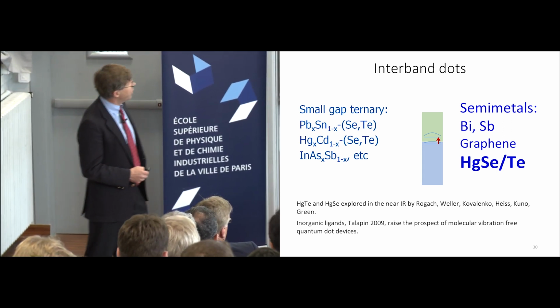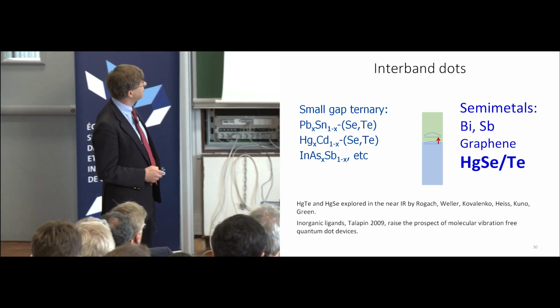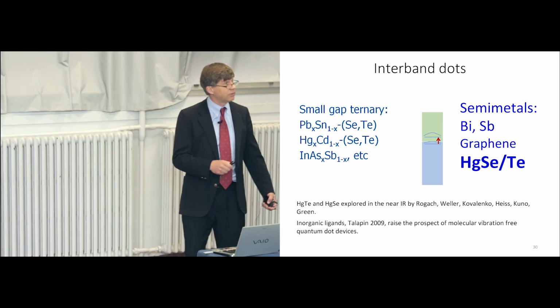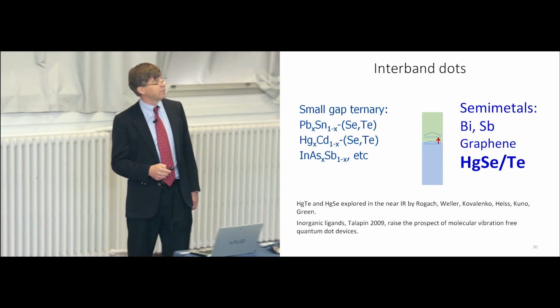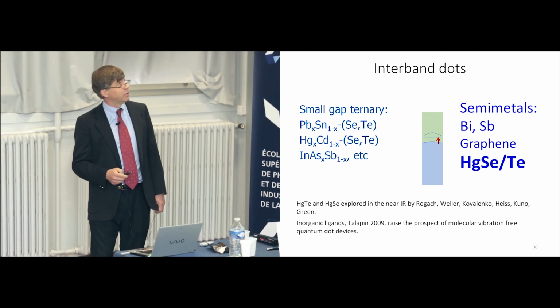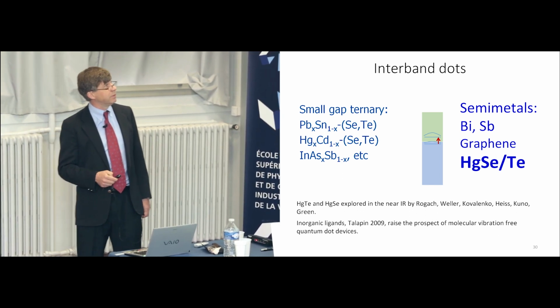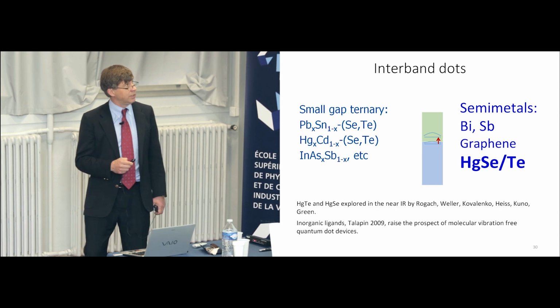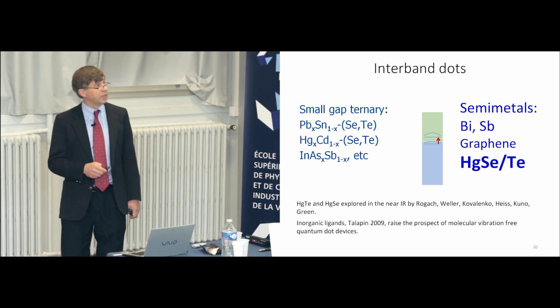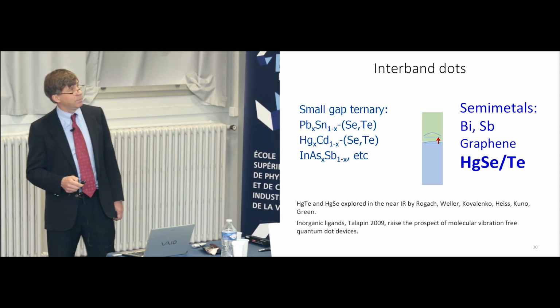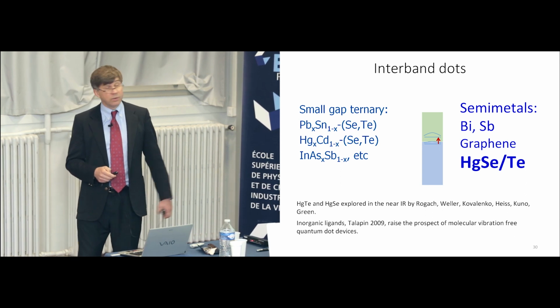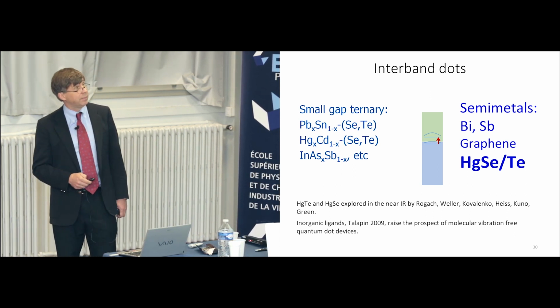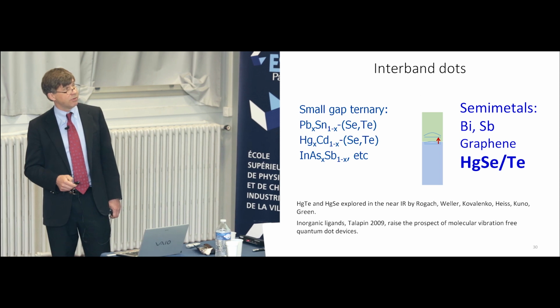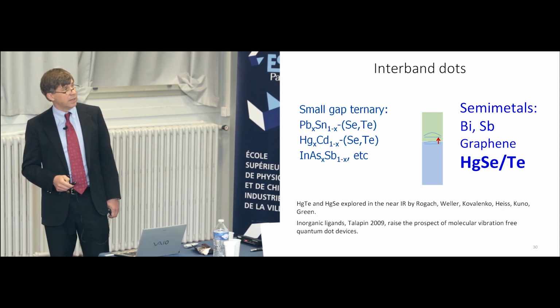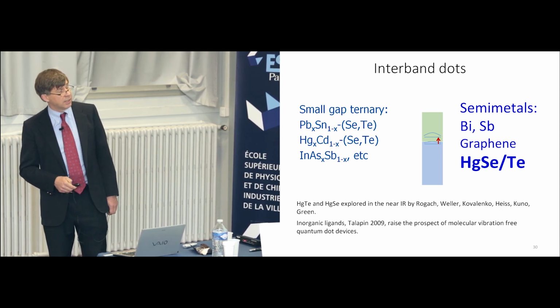So one approach is to use interband dots, so trying to take smaller and smaller gap bulk materials and just make a quantum dot out of it. So the ternary materials are very promising, but you need to be a good chemist to control the composition accurately. So we look for simplifying. Semi-metals is the other option, things with a zero gap. So for example, bismuth, antimony, graphene, very exciting at the moment. And of course, the mercury chalcogenide.